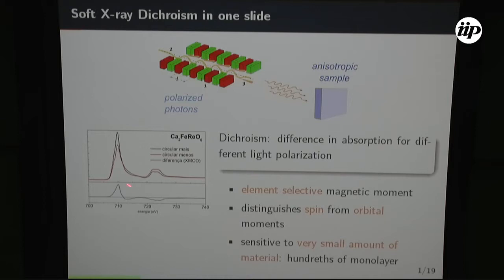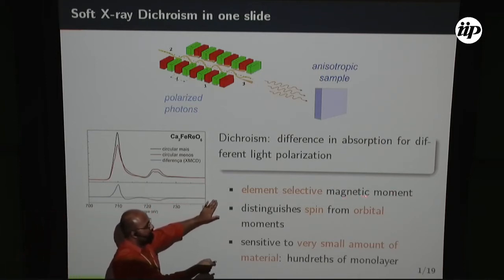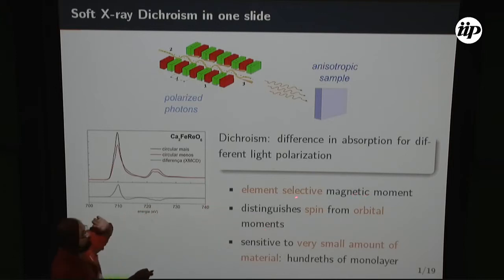And the interesting thing about this dichroic signal is that with very simple sum rules until recently, and more these days based on first principle calculations or multiplet calculations, from this signal you can extract very important magnetic information. Element selective magnetization. For each element, you can separate between spin and orbital contributions. So this is very important. It's very difficult to do that in general.